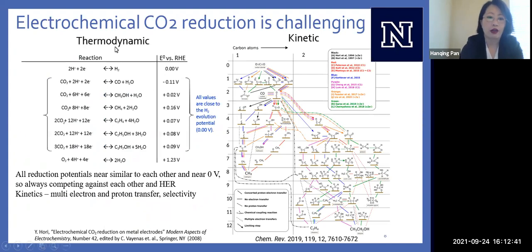And I'll quickly point out, we have to look at the thermodynamics and the kinetics of this reaction. So we start here first by looking at how we can make hydrogen. So if we take 2 protons and 2 electrons, we can make hydrogen, and it does not take a lot of energy to do this. So this is at 0 volts versus reversible hydrogen electrode. It doesn't take a lot of energy, and that's why water splitting is fairly easy to do. Hydrogen evolution reaction is the cathodic reaction from water splitting.